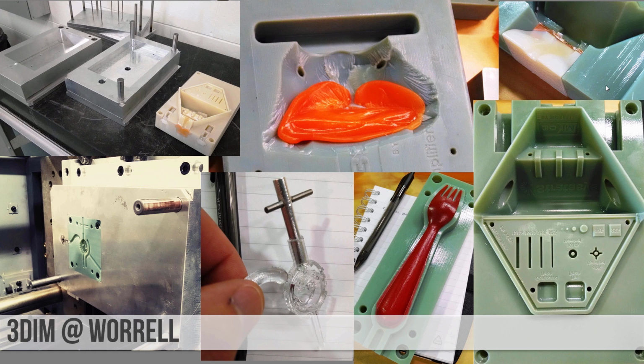And then in the top center there, what you're looking at is the back side of that same mold that's been blown out. So eventually these molds do fail. This one, I was told, failed around the 3 to 4 dozen mark. Okay, and it blew out the back side. That actually could have been prevented, possibly, because what happens as you're molding these parts, the molds tend to change shape slightly, and they sit a little bit cockeyed in the mud box. And so every once in a while, you're pulling them out and you're shimming them back flat. And what may have happened here is that it was time to shim it and they missed it. It was able to blow out the backside. That's eventually how it's going to fail.